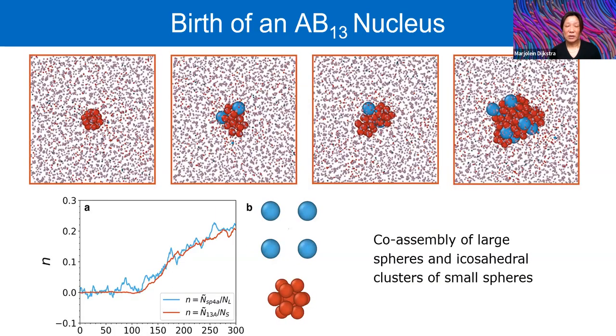We can refer to the morphology of such a nucleation trajectory, and we can really see that it starts with an icosahedral cluster of 13 small particles. Then big spheres are attached to that nucleus. Then more icosahedral clusters are attached to that. If we then plot the number of big spheres and icosahedral clusters that are attached to that nucleus, we see that it is really a co-assembly of large spheres and icosahedral clusters of small spheres, and that really proceeds via classical nucleation theory.